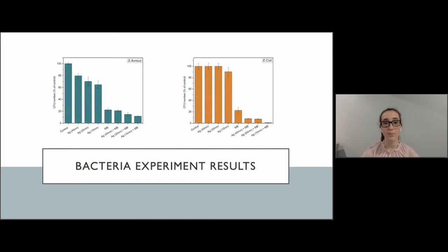According to our results, the methylene blue and silver nanoparticle combination was the most effective at eradicating both the gram-negative E. coli and gram-positive Staph aureus after 5 minutes of light irradiation. With these conditions, we were able to eliminate all of the bacteria present. Methylene blue is able to generate copious amounts of singlet oxygen, which can react with the outer membrane of bacteria and further damage it. This makes it an excellent photosensitizer, which is why we utilize it in combination with the silver nanoparticles and also explains why it was the most effective at eradicating the different bacteria cultures of our samples.